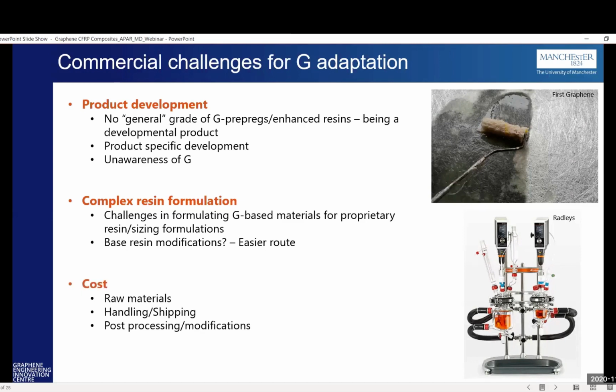Then cost. Still, for some people, cost is also a factor. To be honest, back in 2011, I bought 1 gram of graphene for 500 pounds, whereas now you can buy a decent grade of graphene for under $200 a kilogram. Typically, the loadings of graphene you want to add into fiber reinforced polymers are less than 1%, typically 0.5% in the resin. So you can go a long way.